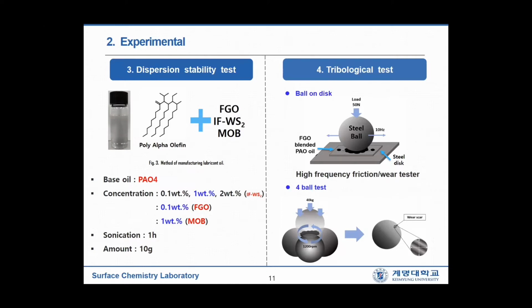We have also applied 0.1 weight% of FGO and 1 weight% of MOB. These mixtures are then ultrasonicated for an hour and left for 30 days. Then we carried out tribological tests with this high-frequency friction wear tester.